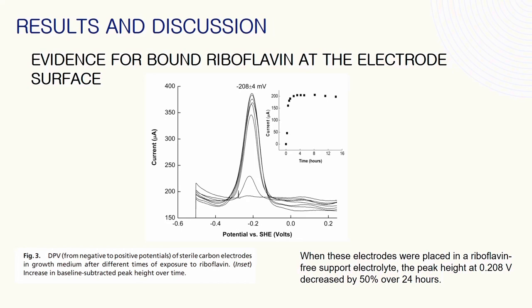When scanning from negative to positive potential, a peak centered at 0.208 volt was detected within 15 minutes, and this peak height reaches its maximum in 60 minutes. When these electrodes were placed in a riboflavin-free support electrolyte, the peak height at 0.208 V decreased by 50% over 24 hours. Riboflavin 5-phosphate also exhibited rapid adsorption and binding to electrodes in DPV analysis.